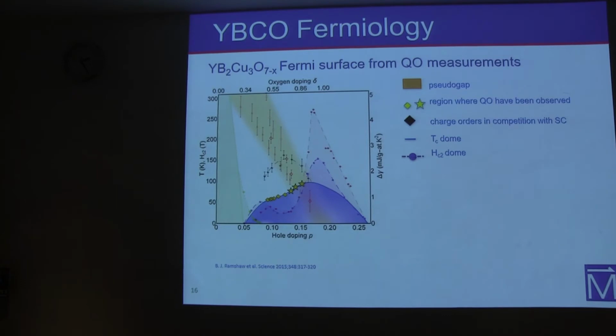So I show here again a different picture of the phase diagram of YBCO. If we want to measure quantum oscillations, we have samples available up to here, to optimal doping. Those symbols here are the various dopings where quantum oscillations have been measured using transport measurements, for example. To measure quantum oscillations, you have to be in the normal state of the sample, so you have to somehow suppress the superconductivity. To do that, we have to apply a high magnetic field.